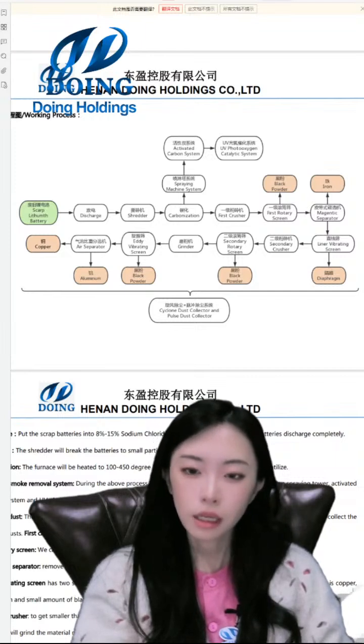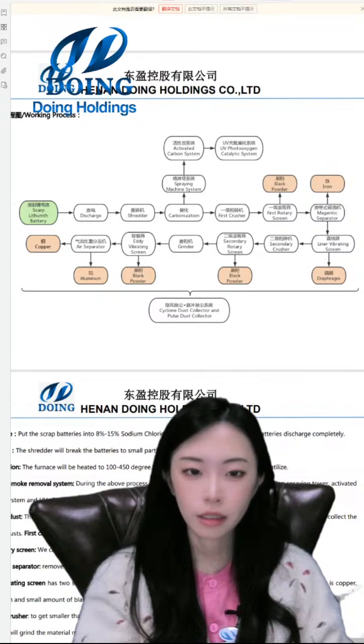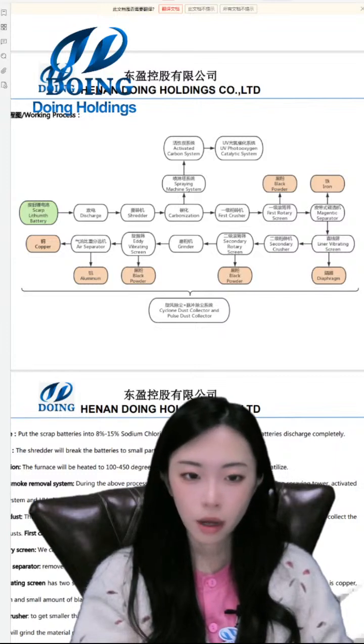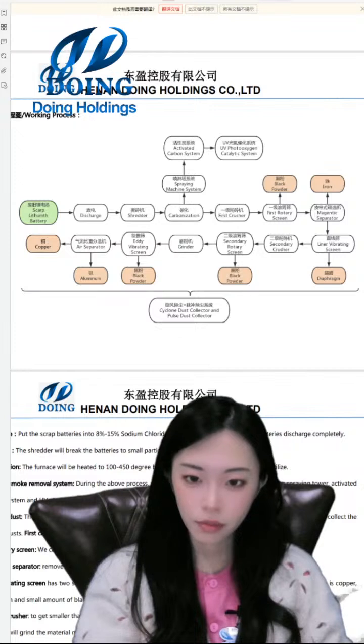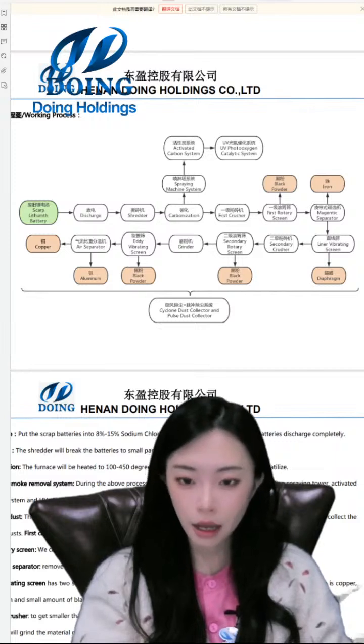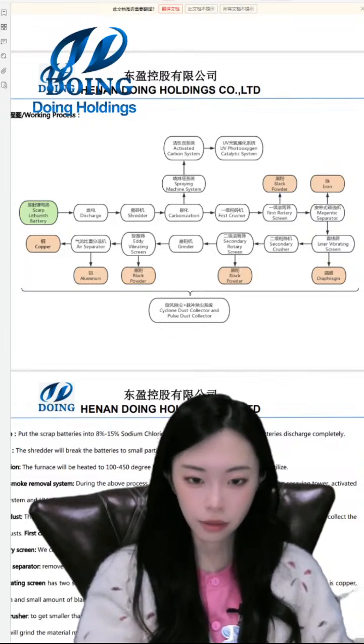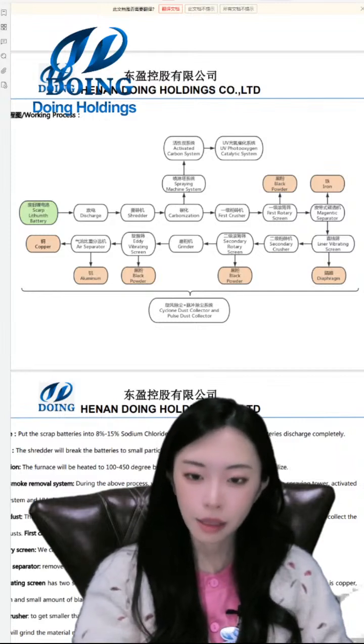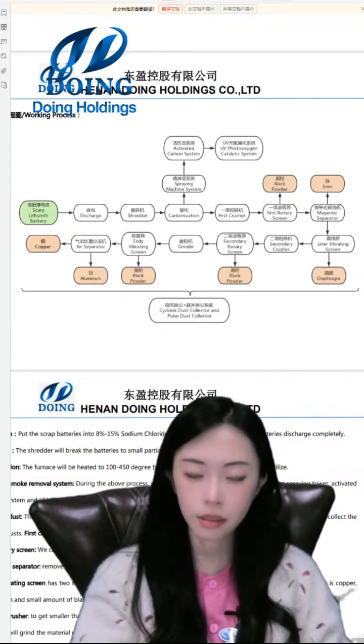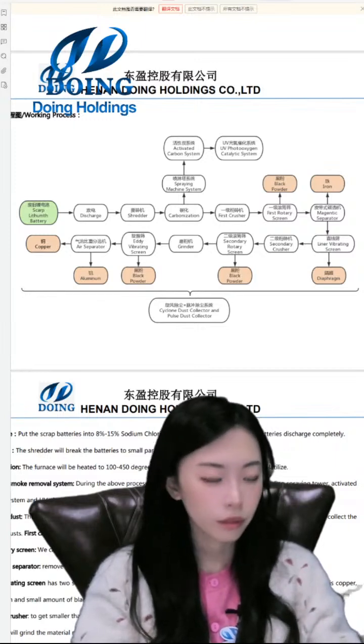And then this is the linear vibrating screen. The linear vibrating screen uses vibration to separate the different products. It has 2 layers, one is 2 millimeter and one is 100 mesh, and this is stainless steel. The top layer of the screen is for the diaphragm, equipped with pipes and fans to remove the plastic diaphragm. The middle layer is copper, aluminium, and black powder. The bottom layer is the black powder. The recovery rate of the diaphragm is 98%. In this step, almost all the diaphragm is recycled.